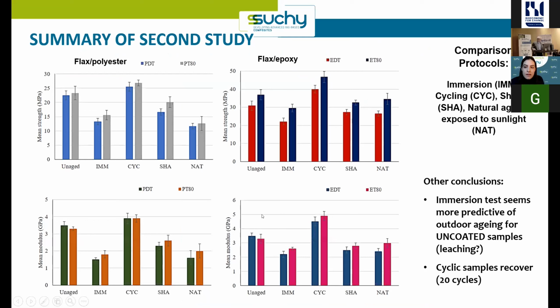So here you see some summary of many results. Actually, the upper results are for the strength, the lower ones for the modulus, and the left column is polyester, and the right column, epoxy. But in all the cases, we see very similar things. So maybe focus here on the tensile strength of the flax epoxy.